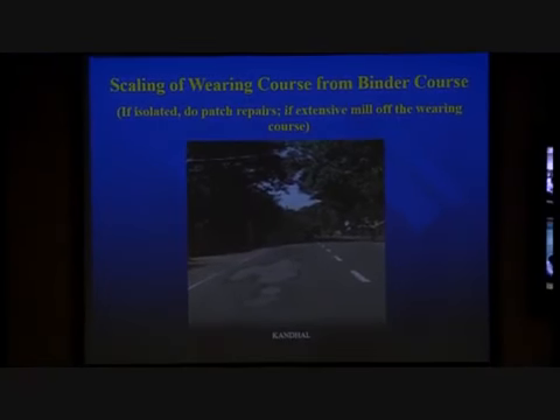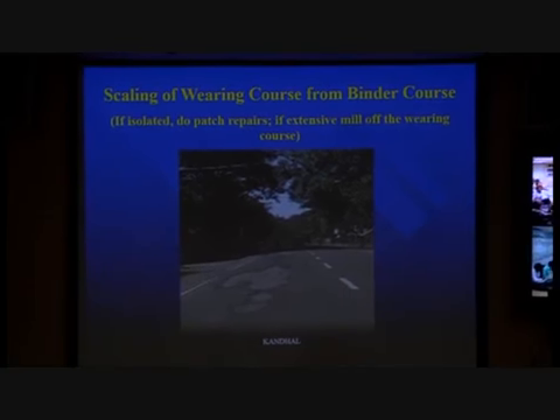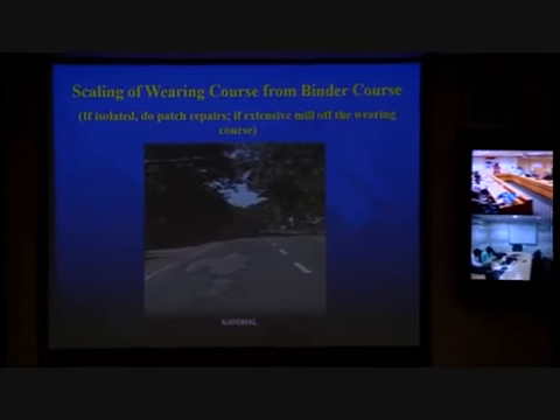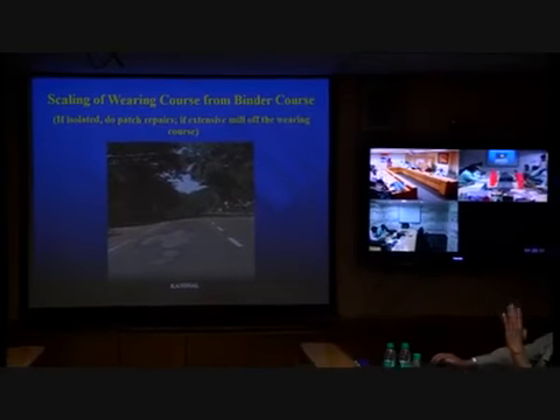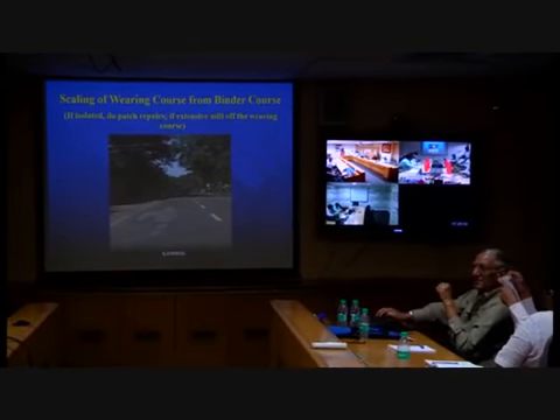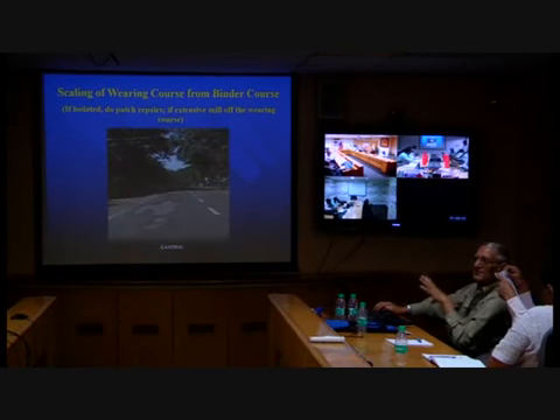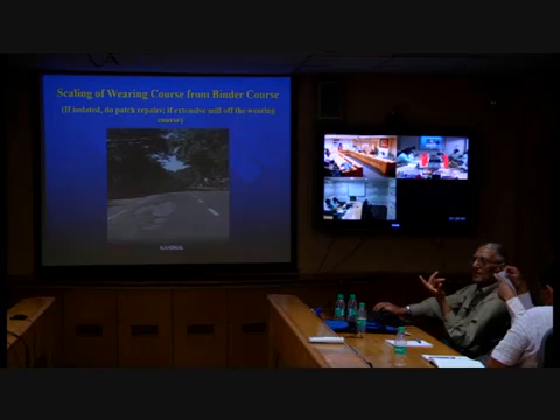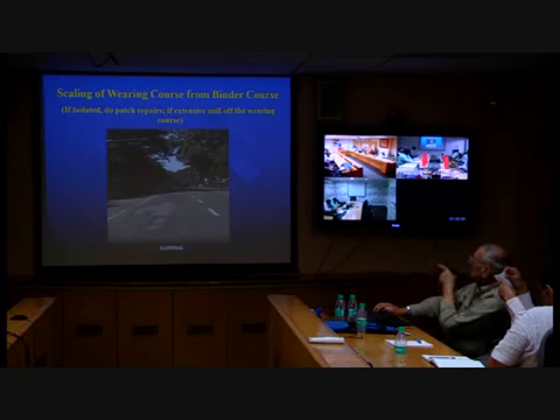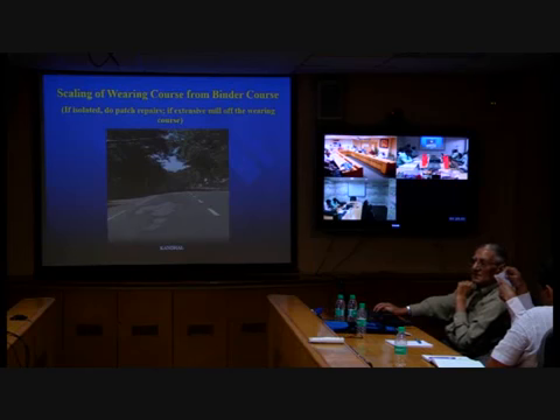Here is just called scaling of wearing courses from binder courses. I have seen a lot of scaling in India wherever we have put SDBC on top of BM. BM with SDBC is very common in India because they are very cheap. BM is very cheap, SDBC is only 25 millimeter thick. So everybody does that. BM takes a lot of air voids, so it will take up all the water. So water will get filled, the stripping will take place, and there will be debonding between the SDBC and the BM. This is a case from Kerala, where SDBC has been scaled off.